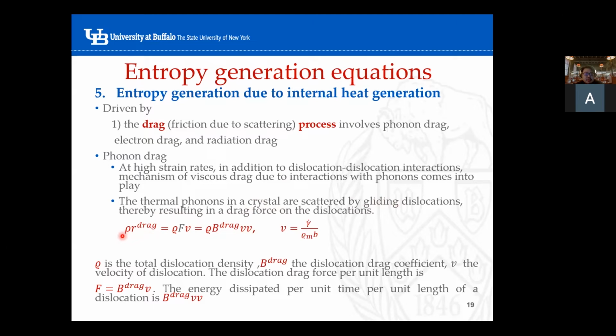So the total internal heat generated, rho density times the amount of heat generated per mass during the drag mechanism, is equivalent to the total dislocation density times the dislocation drag force per unit length times the velocity of the dislocation. And the drag force per unit length of the dislocation is equivalent to this drag coefficient B drag, again times the velocity of the dislocation.